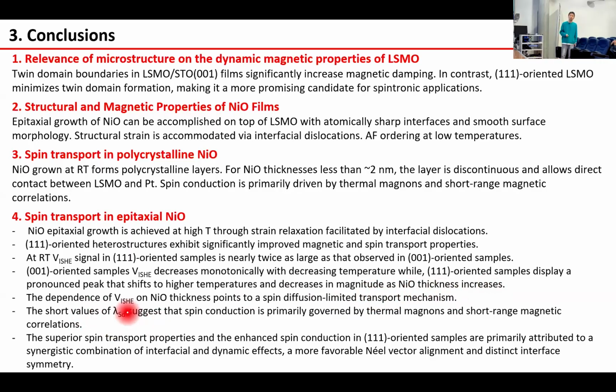The dependence of the inverse spin Hall voltage on the NiO thickness points to a spin-diffusion-limited transport mechanism, and the short spin diffusion length suggests that the spin conduction is primarily governed by thermal magnons and short-range magnetic correlations. The superior spin transport properties and enhanced spin conduction in the 111 oriented sample are primarily attributed to a synergistic combination of interfacial and dynamic effects, a more favorable Néel vector alignment, and distinct interface symmetry.